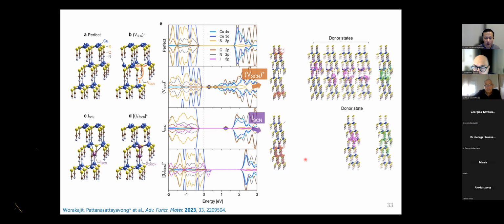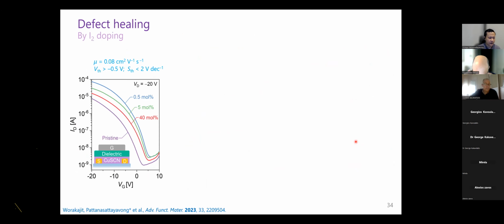This is more some visualizations of the defect state. So the donor states here, once substituted by the iodine, are eliminated. And yeah, the performance gets better. The transistor gradually gets better at the optimal concentration. Too much iodine, then it's not good. Then it becomes like impurity defects inside.